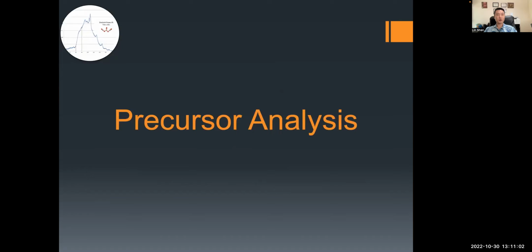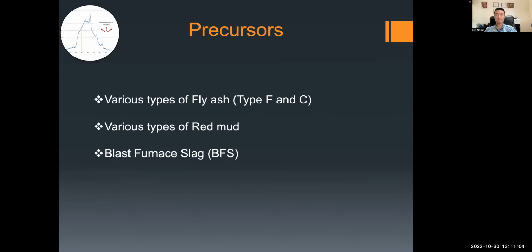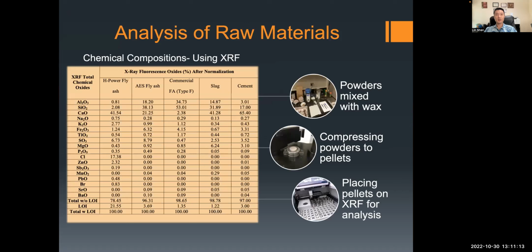Next, I will show you the precursor analysis. We use fly ash, different types of red mud, and slag. And here shows XRF, which can give us the basic information of the percentage of different types of oxide. However, XRF alone is not enough.